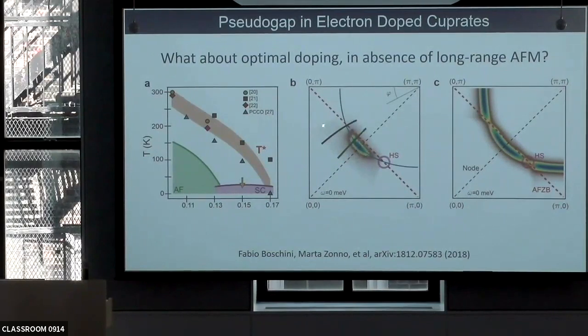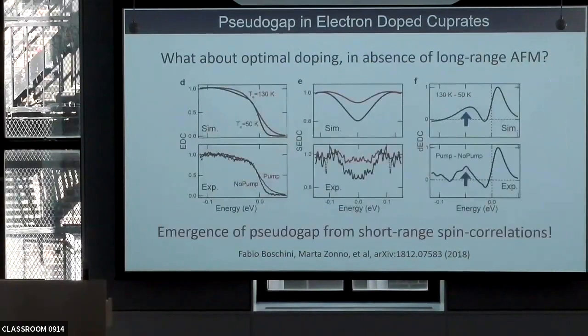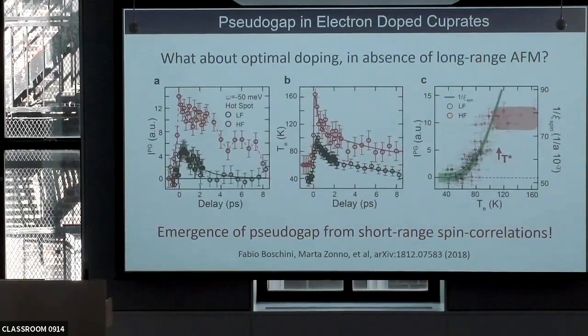These have again been measured with a 6 eV laser. So we're bound close to the nodal direction, not all the way to the antinode. And what Fabio's done, in addition to taking a Fermi surface, is compare data taken close to the nodal direction with data close to the hotspot itself. Let me go directly into the dynamics of the signal. Then, for people who are interested, I can tell you how he extracted that.